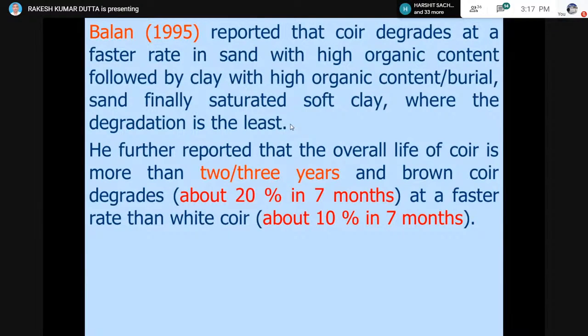Though I have not included that data, I'm just telling you that many different kinds of media were tried. On the basis of this entire study reported in this PhD thesis of Dr. Balan, they came to one conclusion: the overall life of the coir varies between 2 to 3 years, and the brown coir degrades at about 20% in 7 months, a faster rate in comparison to the white coir, which is about 10% in 7 months. Meaning thereby that the degradation is going to be up to the order of 20% in case of brown coir, whereas it is going to be around 10% in a period of 7 months in case of white coir, right? So we need to keep all these aspects in mind